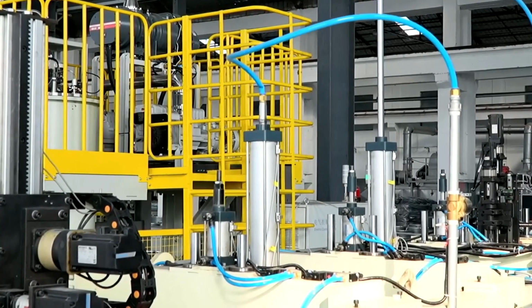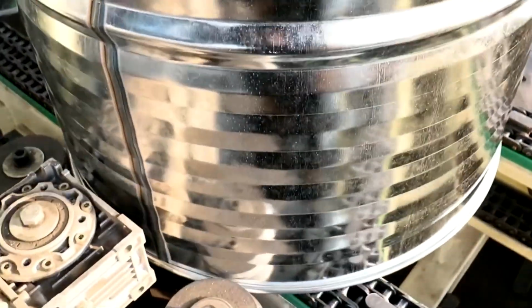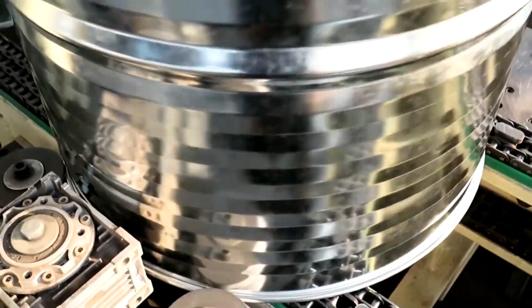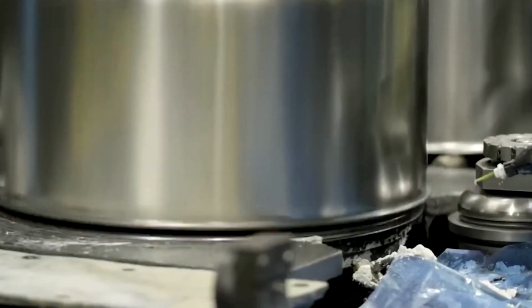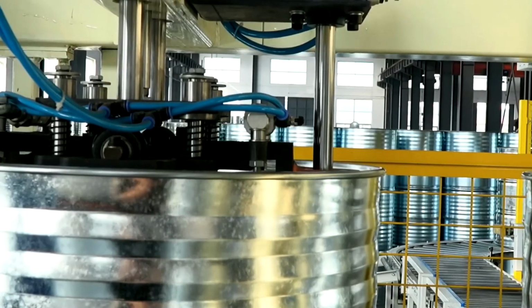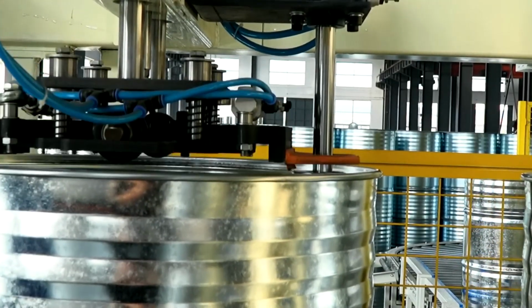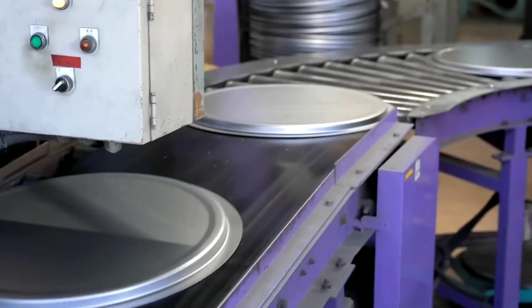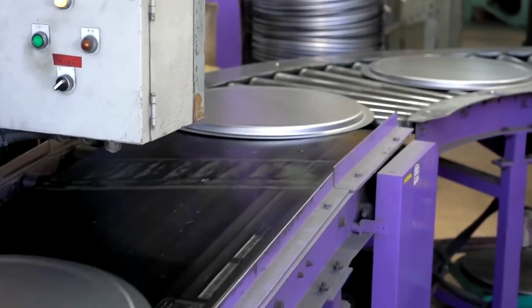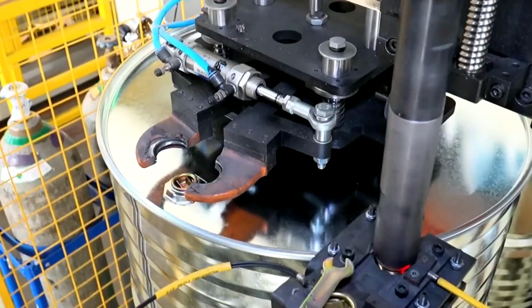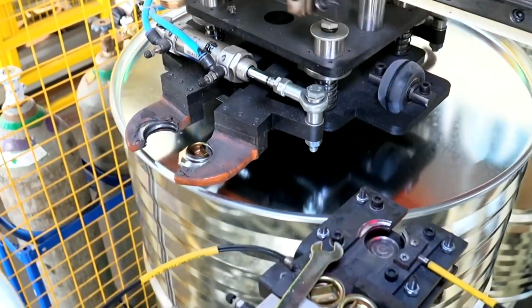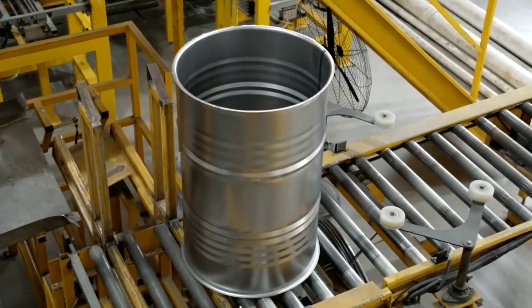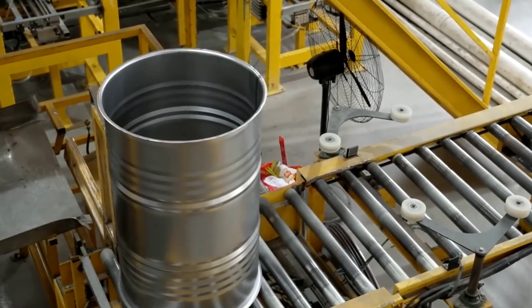Automated conveyors transport the assembled components into a heavy-duty rim rolling machine. Once the lid and bottom are seated, steel rollers begin to apply substantial mechanical force, compressing and flattening the edges that were pre-rolled during the earlier stages of fabrication. This intense pressure creates tight sealing ridges, known as chimes, that encircle the top and bottom rims with absolute uniformity. These chimes function as the primary structural lock, fusing the lid and bottom to the body to ensure the unit can withstand significant internal pressure.